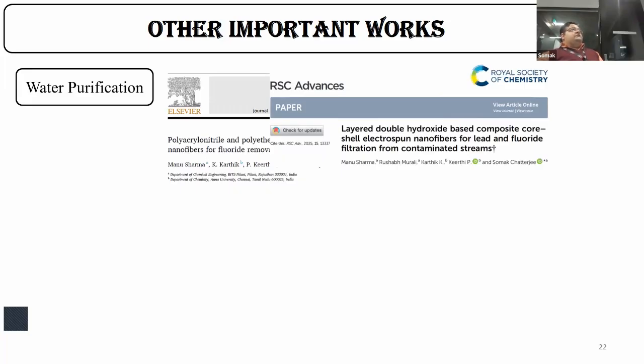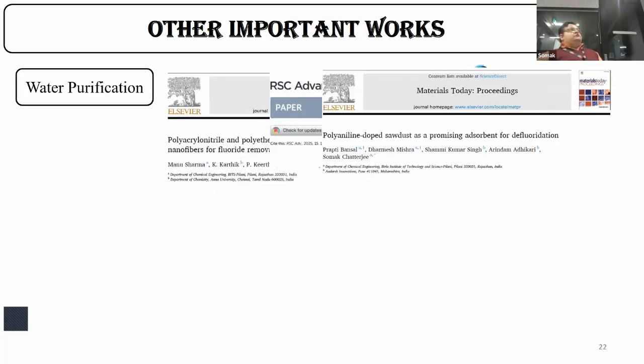That is again used for fluoride removal. But again, we used a micropollutant over here, which is a harmful heavy metal, that is lead. We used composite polymers, which are conductive polymers like polyaniline, for defluoridation, and we used both undoped and doped forms to see how it can affect defluoridation and lead removal. The doped polyaniline based material shows promise as an adsorbent for fluoride removal, whereas undoped polyaniline can be used for lead removal, because of the charges imparted in the conductive polymers and the functional groups as well.